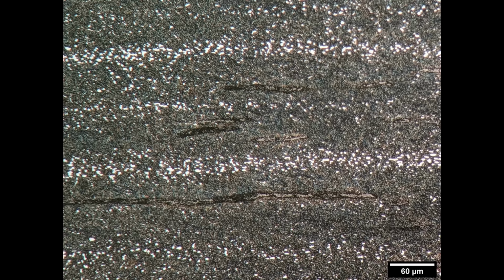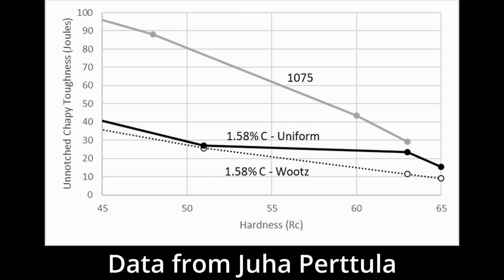The other reason is the banded carbide structure. So bands of carbides are worse for toughness than evenly distributed carbides. So again, Perttula did a study where he looked at 1075, that's 0.75% carbon, versus a 1.58% carbon Wootz material, very close to the carbon content we are studying. As expected, the 1075 with lower carbon had significantly higher toughness at the same hardness.